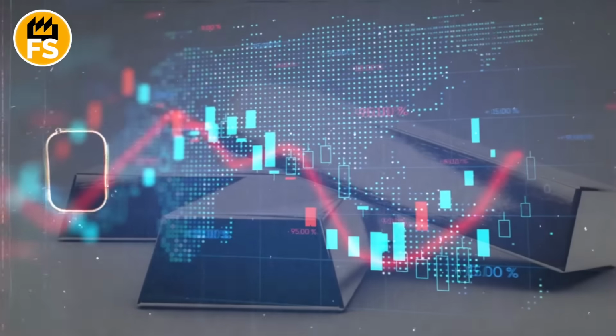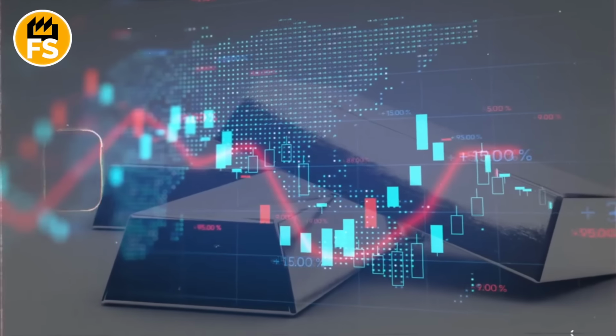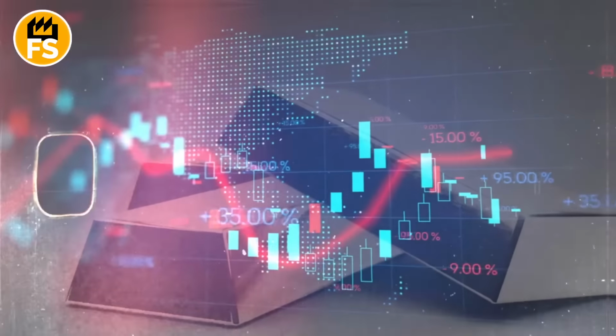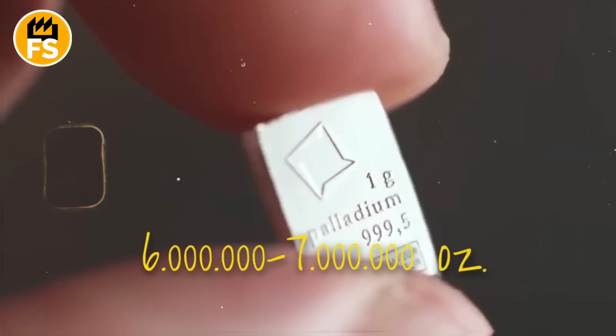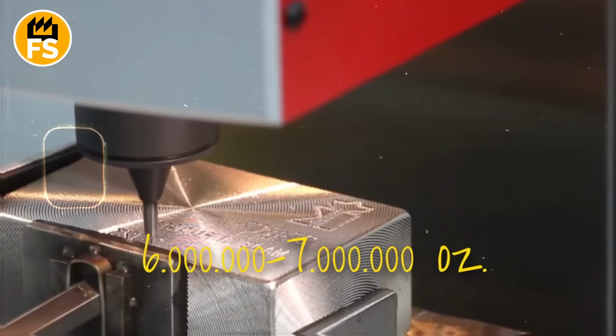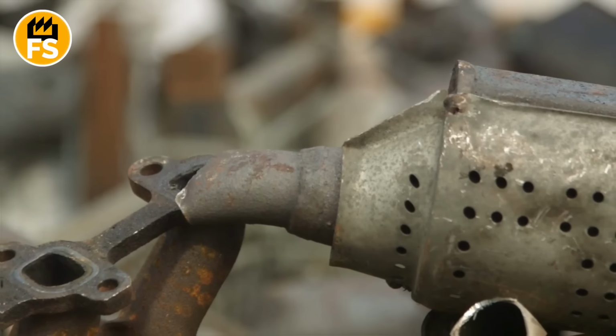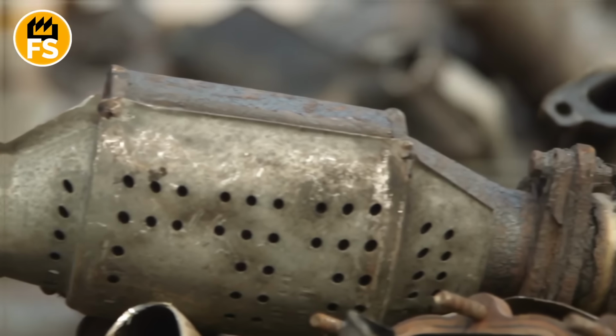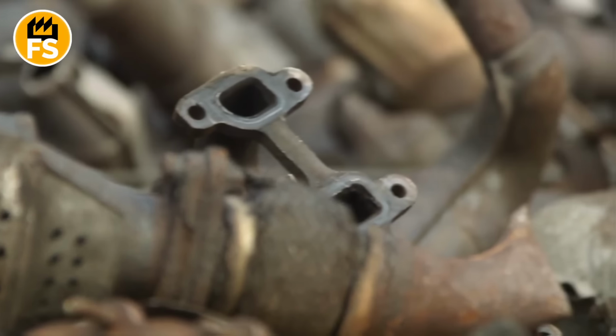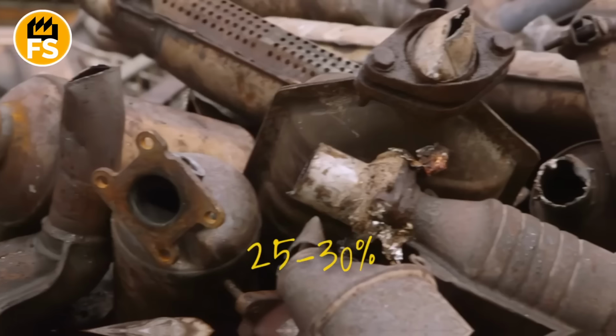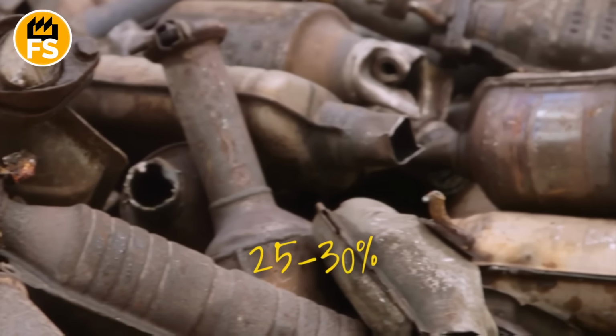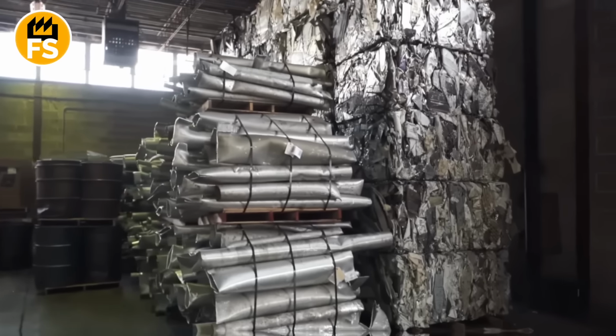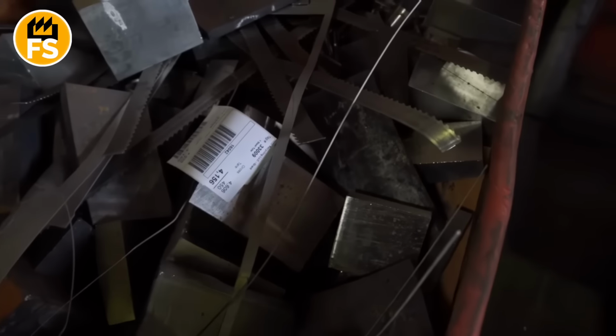Global palladium production is typically measured in the millions of troy ounces per year. On average, worldwide output hovers around 6 to 7 million ounces annually, with more than two-thirds of that volume coming from just two countries. Another key figure, secondary recycling, mostly from used automotive catalytic converters, accounts for 25 to 30% of global supply. By comparison, for many other precious metals, the recycling share is significantly lower.